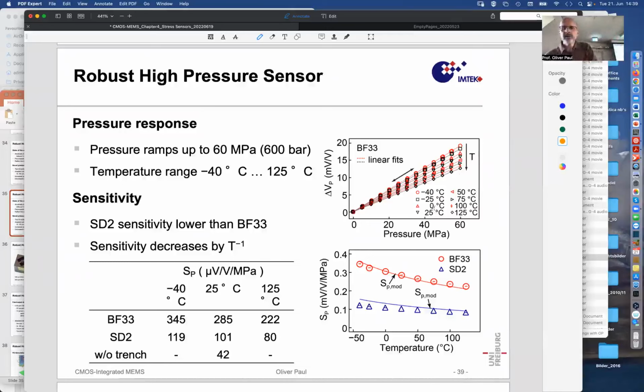You see that the higher the temperature, so this is cold, minus 40 degrees centigrade, and this is the last one, 125 degrees centigrade. Typical automotive specifications. Now that's not the temperature in the center of a motor where the pressure is being measured. It maybe indicates that the pressure will not be measured in the combustion chamber, but somewhere else where it is transmitted by another element onto that sensor. Don't expect this silicon glass component to be exposed to the combustion itself. But anyway, this is the temperature range that he studied, and well, you see that it's highly linear. Temperature range is also okay.